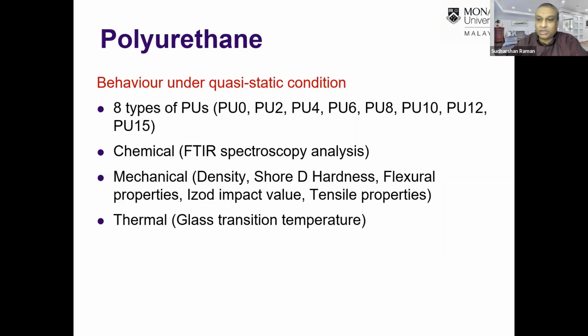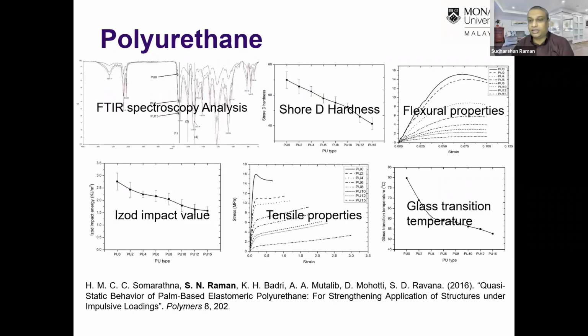We characterized its chemical properties and the mechanical properties as well as thermal properties. The mechanical properties characterized under quasi-static condition were density, Shore hardness, flexural properties, Izod impact value, and we also performed direct tensile tests. And these were published in the year 2016 in the journal Polymers. Okay, the entire comprehensive results were presented in this study.